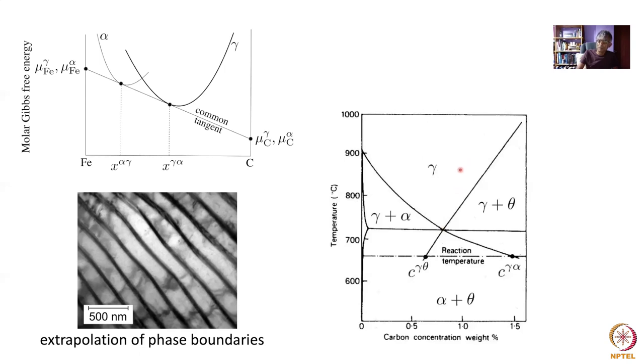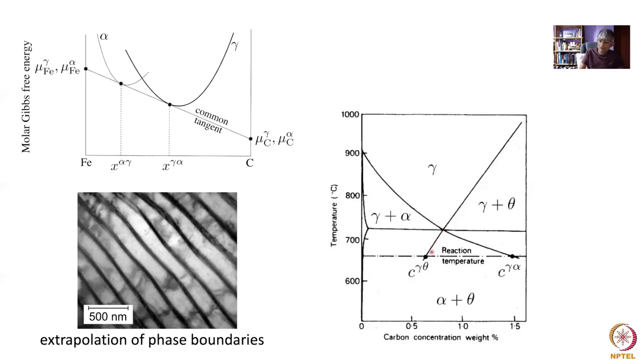Within this extrapolated region, it is possible for both cementite and ferrite to grow simultaneously from austenite, meaning that to obtain a fully pearlitic structure the composition need not be exactly the eutectoid composition. Suppose we have a hyper-eutectoid steel and super-cool it to avoid precipitation of cementite — it's possible to get a fully pearlitic microstructure, albeit with a larger fraction of cementite in the pearlite. Similarly, for a hypo-eutectoid steel avoiding ferrite precipitation, you can also get a fully pearlitic microstructure. This region is known as the Hultgren extrapolation region.